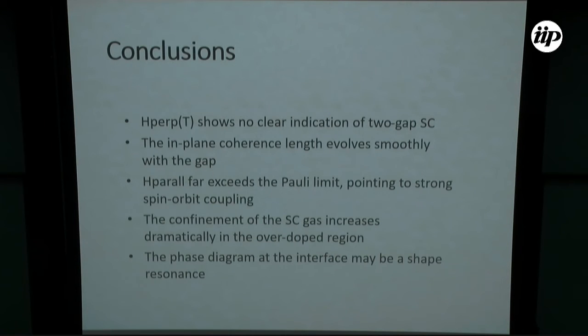And with that, I'm coming to my conclusions. The experiments in parallel and perpendicular field do not show indication of two-gap superconductivity, as has not been observed by the other techniques for SrTiO3, both from tunneling or from SQUID experiments. There's been no signature of this two-gap superconductivity in SrTiO3 or in LaAlO3. Also, what we don't see is the presence of the pseudogap in the underdoped regime. So we see a one-to-one relation between the in-plane coherence length and the gap in the system. And then, as I said, we have an excess of the parallel field pointing to a spin-orbit coupling in the system.